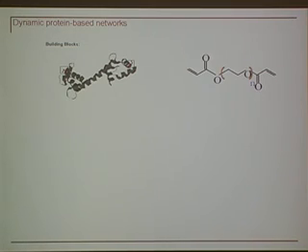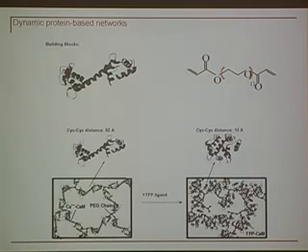So the concept here is that the sulfhydryl groups on the end of cysteine can react with acrylate groups via Michael-type addition reaction that then results in a covalent linkage. And then once purified, this would result in the presence of a protein that's linked on both ends to PEG acrylate and therefore can be photo-cross-linked into a three-dimensional network.